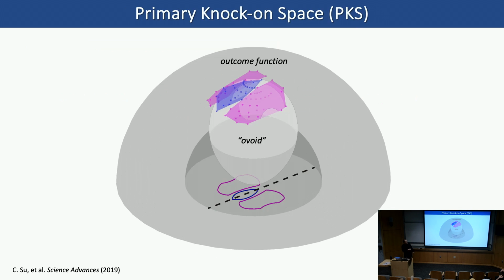If you combine the ovoid, we still remember there's an ovoid representing the initial status of that atom, if you combine these two together, there will be an intersection area which marks the active dynamic region. Basically, it tells you that once your carbon atom is being kicked by an electron and is scattered to this, what would the dynamic outcome look like? So if there is an intersection between these two things, it means there's a probability that this dynamics could be an outcome. So by calculating the ratio of these different intersections actually marks the probability of different atoms, how it would look like when it's being kicked by an electron.